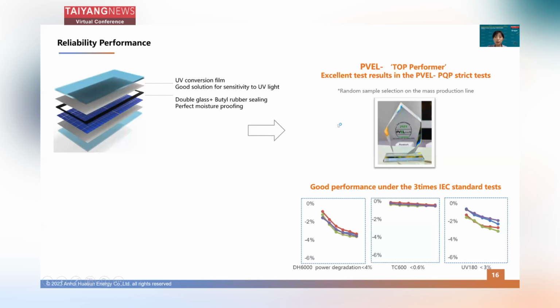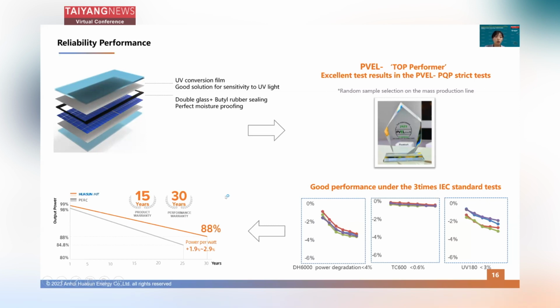And not only the PVEL test, internally and externally, we have also done the 3 times IEC standard test, including DH, TC, and UV. All these 3 times IEC test results show much limited power degradation. Based on these reliability test results, we are confident to provide customers a 15 years product warranty and 30 years performance warranty, with 1% first year degradation and 0.375% degradation annually.